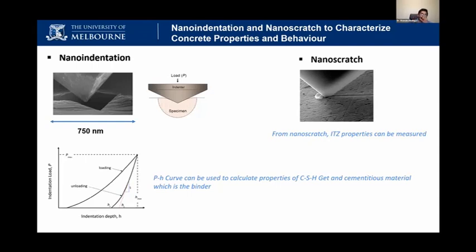So we use a very innovative method called nano indentation. Nano indentation is indentation at the nano scale. You can see this is a tip. You can indent the cement or the paste using this nano scale diamond tip, which is like 750 nanometers. From that, we can get the load and the depth, that relationship. And we can also use the same tip to scratch the surface, and find the properties of the surface.